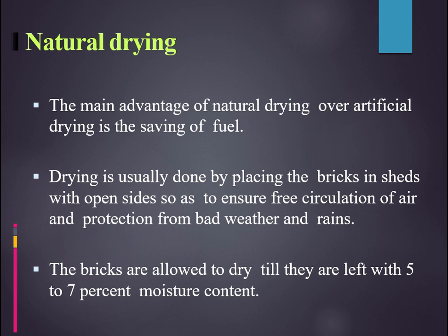Okay. So they are shed-like structures, right? The top surface will be closed and the sides will be a little bit open. As told, you can see in the last point, the bricks are allowed to dry till they are left with 5 to 7% of moisture content. So up to 7% of moisture content will be left in the drying process, and once it goes for the burning process, this moisture content will also evaporate.